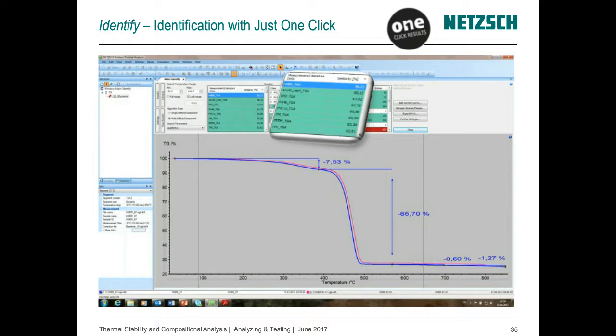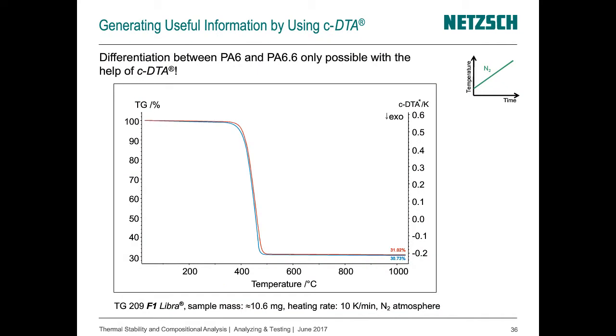Some slides before, I told you already that unfortunately not all decomposition profiles are specific enough for polymer identification. And this is an example which shows this situation. We have here two curves, a blue one and a red one. One comes from the measurement of PA6, so polyamide 6, and the other one is derived from a measurement of polyamide 6,6. But from these curves itself, it's not possible to say which curve belongs to which material. Is the red curve polyamide 6,6 or is it polyamide 6?